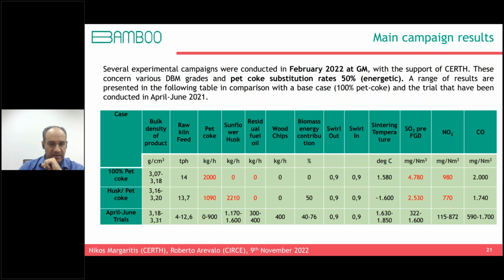When we used sunflower husk pellets with petcoke, you can see that we have petcoke at a flow rate of 1,000 kilos per hour, and we have also sunflower husk in the fuel mixture. We have a 50% contribution of biomass to the petcoke energy, at almost the same temperature. And here we can see that with the introduction of biomass, we have an extra reduction of SO2, NOx and NO2 emissions. This is about 20% extra NOx reduction. In total, with this biomass substitution, you have a 6% reduction in NOx.